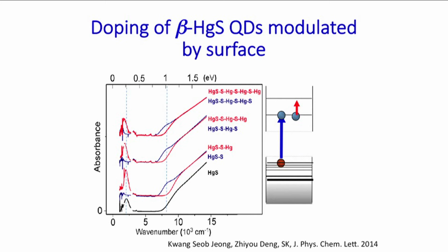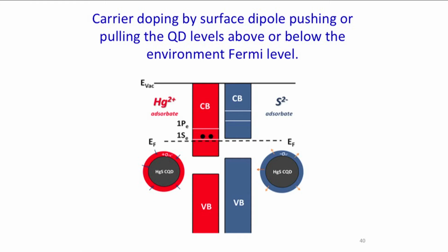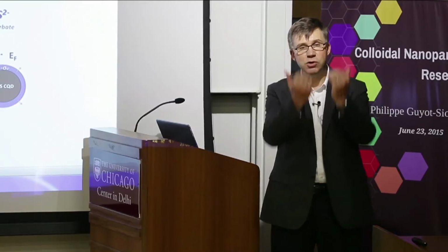And so what those things are doing is really this. Either we're in these situations when we have a surface that's mercury rich, or we are in this situation when we have a surface that's sulfide rich. So we put electrons in or put electrons out. Are we actually putting the electrons from the surface? We don't think so. The interpretation we have of this is simply that it's like the work function change when we put something on the surface. All we do is change the electrostatics around the particle. We have, let's say, a dipole layer that's pushing all the levels up or pulling all the levels down, depending on the orientation of that dipole. And so all that the surface does in this case is not transfer electrons by adding sulfide or adding ions of any kind. It's just moving them up and down.